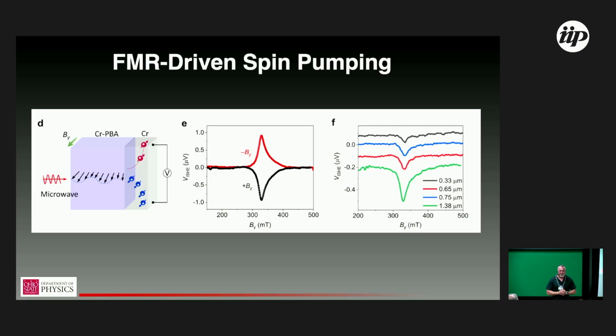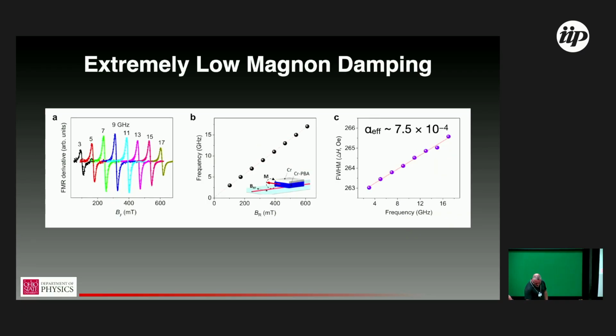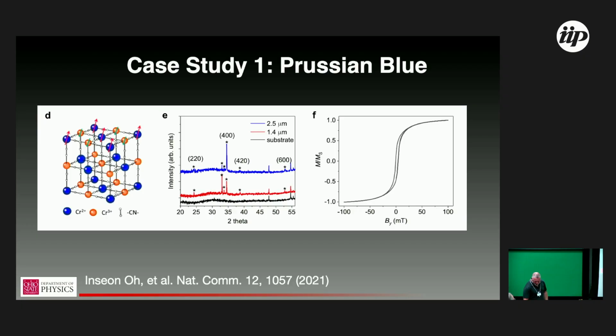I certainly have one. It's the obnoxious one: Zeke, what is the saturation magnetization of this material? I actually checked for that. They didn't quote it directly, and I ran out of time to extract it. But you can ballpark it from the hysteresis curve, the saturation curve. This is not exactly quantitative, but basically the field at which it saturates is proportional to the saturation magnetization with some coefficients out front. So it's in the ballpark of 100 millitesla, or 1,000 Gauss, if you prefer those units.